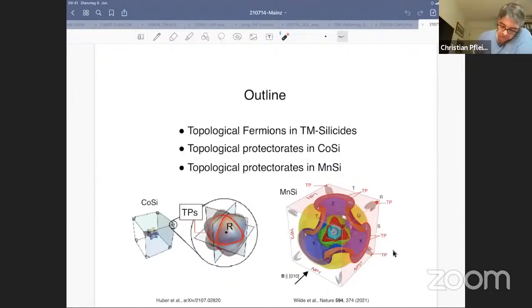Yes, so then after this cobalt silicon, which is a non-magnetic material, I want to address work on MnSi. And you can ask the question, where do these nodal planes basically come from? The nodal planes are the result of non-symmorphic symmetries in combination, and they require time reversal symmetry to be conserved, right? But if you break time reversal symmetry, you can basically suppress these nodal planes. And that is shown here.